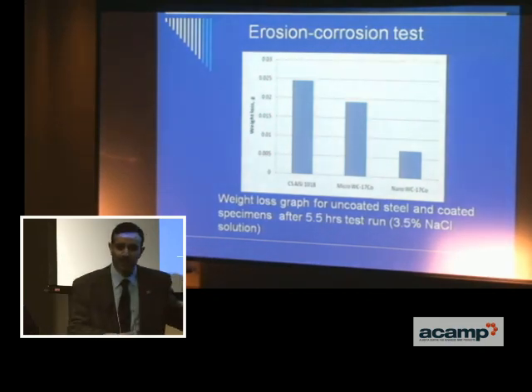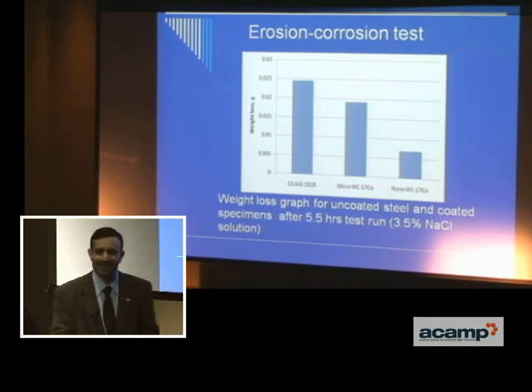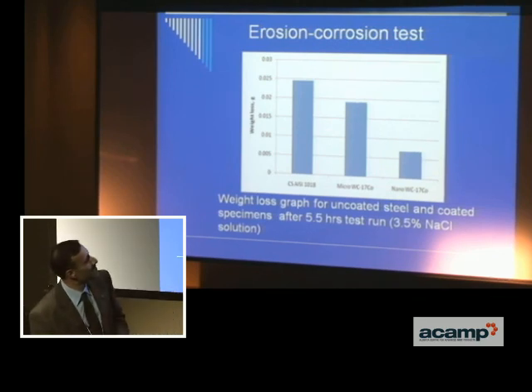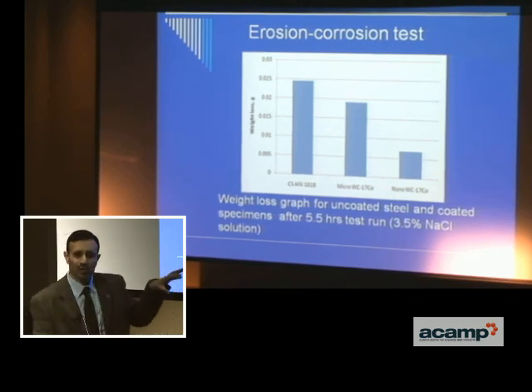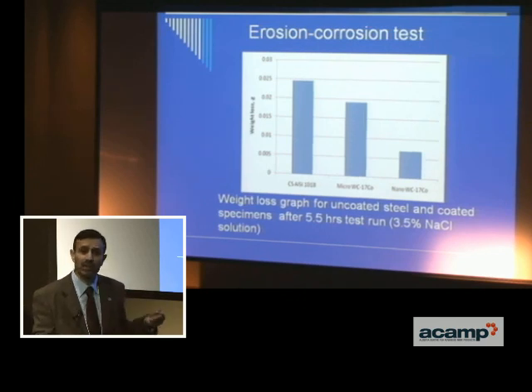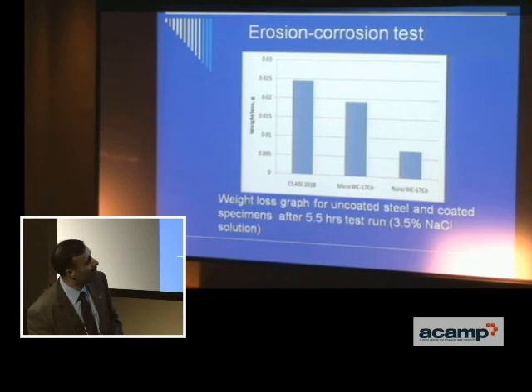I've kept it very simple. There's much more data that I could have presented. I was told this is a talk for a couple of minutes, so I'm pushing myself. This is just an erosion corrosion test. We usually can't ignore the corrosion aspect that takes place in this industry, so we were tempted to put this data here as well. And the nanostructured material shows much better erosive corrosive behavior as well.